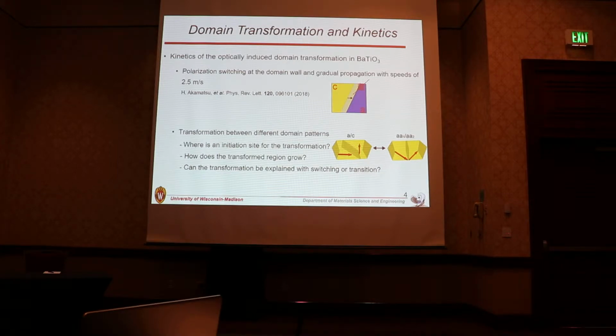And recently, Dr. Akamatsu has shown that optical excitation can change the domain patterns in barium titanate, specifically AC domain patterns. It showed that optical excitation can induce a surface electric field and make the transformation from the A domain propagating to the C domain propagating to A domains, and he explained this by optically induced polarization rotation and domain wall. He measured a propagation speed of 2.5 meters per second. But that system has micrometer scale domain patterns.